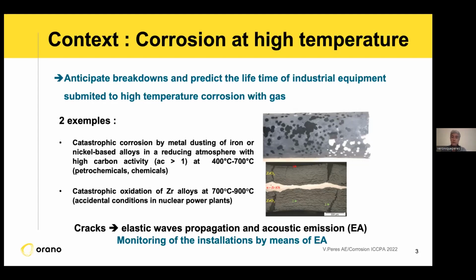The other one is a catastrophic oxidation of zirconium alloy in case of a nuclear plant accident. In this case, you can also have a very aggressive oxidation of the nuclear fuel tubes, and propagate the accident in all the plant. We can see that with holes and cracks, it can generate some elastic waves and propagate. And if we use acoustic emission, maybe we can detect the moment of these corrosions. By monitoring the installations with acoustic emission, it will be very fruitful to know about corrosion.